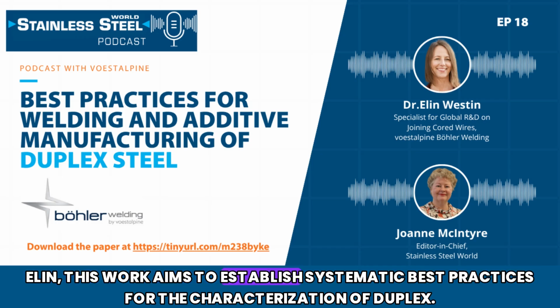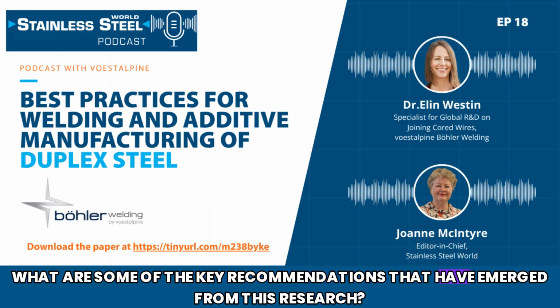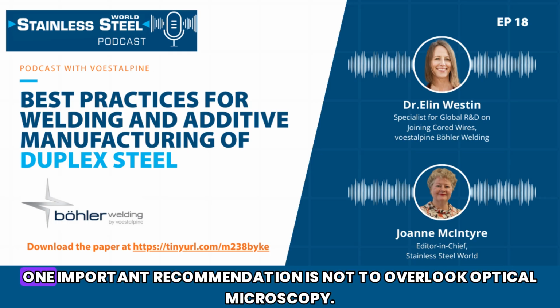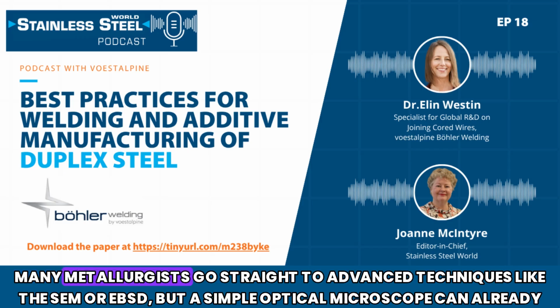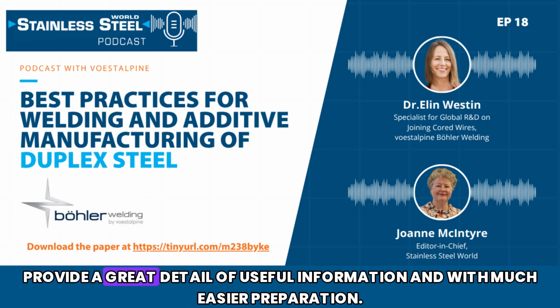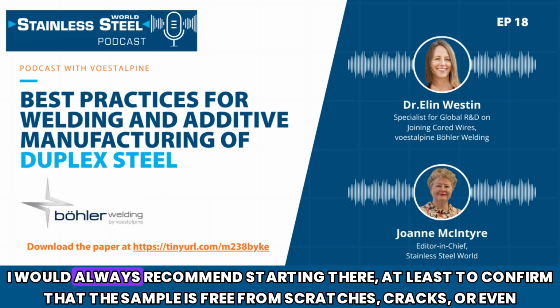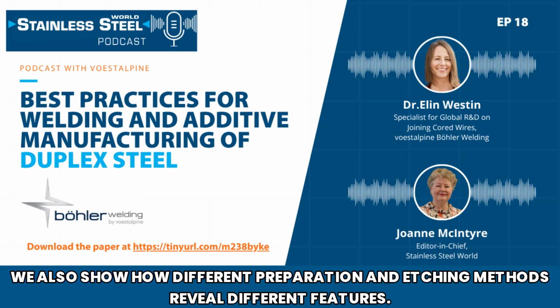Elin, this work aims to establish systematic best practices for the characterization of duplex. What are some of the key recommendations that have emerged from this research? One important recommendation is not to overlook optical microscopy. Many metallurgists go straight to advanced techniques like the SEM or EBSD, but a simple optical microscope can already provide a great detail of useful information and with much easier preparation. I would always recommend starting there, at least to confirm that the sample is free from scratches, cracks, or even drying stains. We also show how different preparation and etching methods reveal different features.